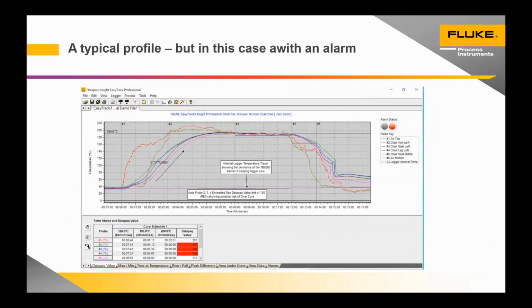So this is a typical report from a Datapaq profile run. What we can see here is that we're using the professional software, so the process manager has set up some alarm conditions. We can see in the top right, the operator has downloaded the information and is immediately presented with a red light. The Datapaq value, which is a measure of the cure index, in this case has been exceeded on 3 of the thermocouples.